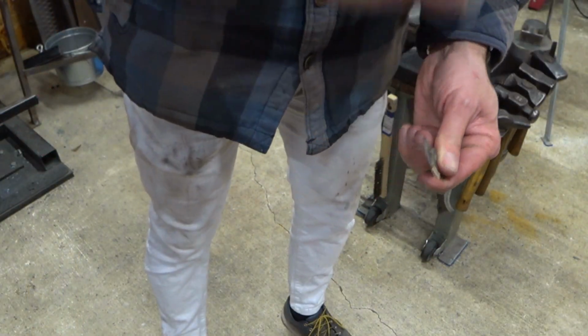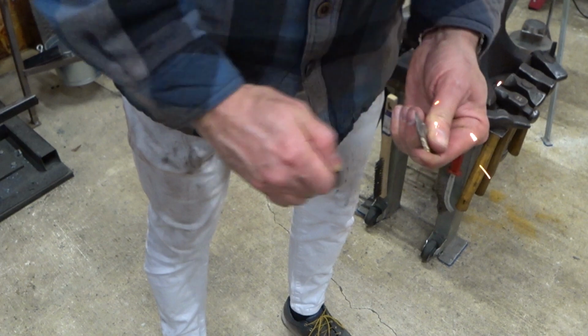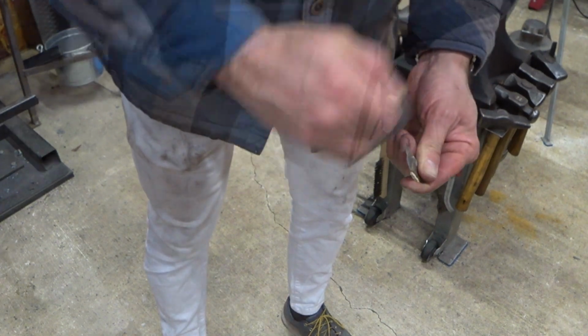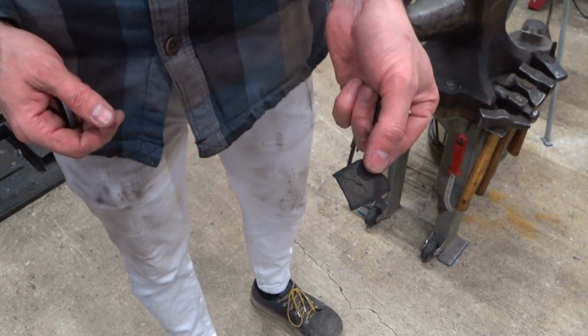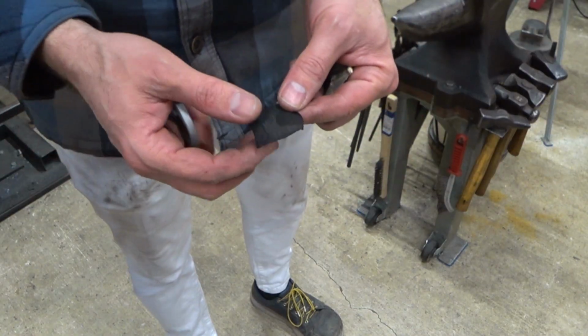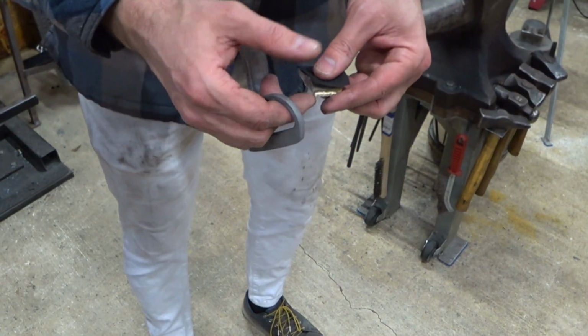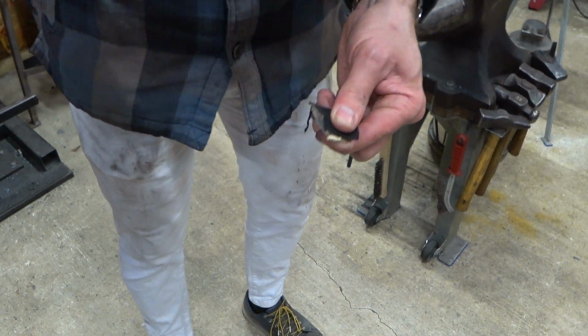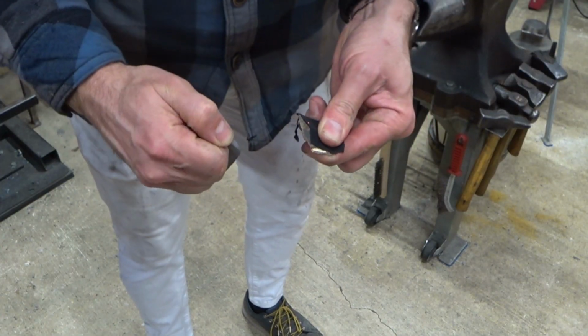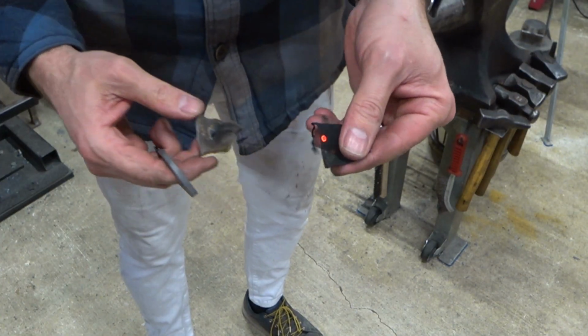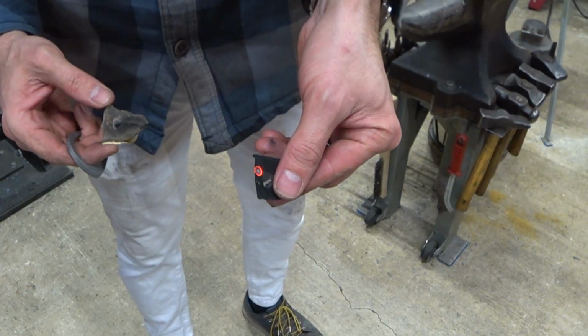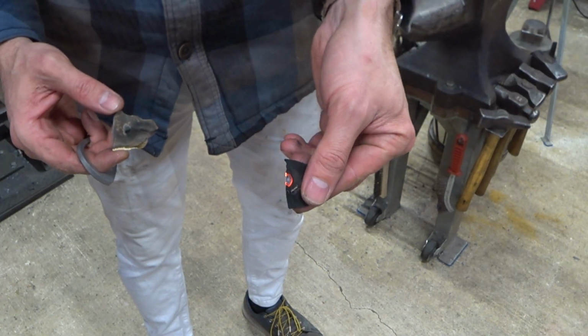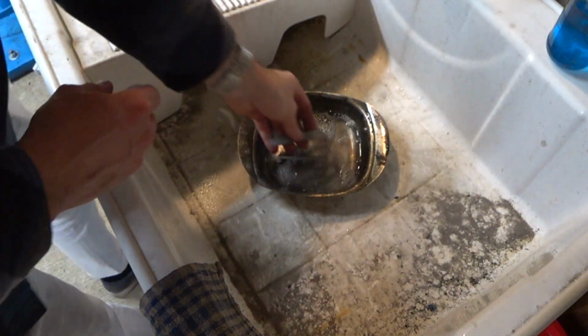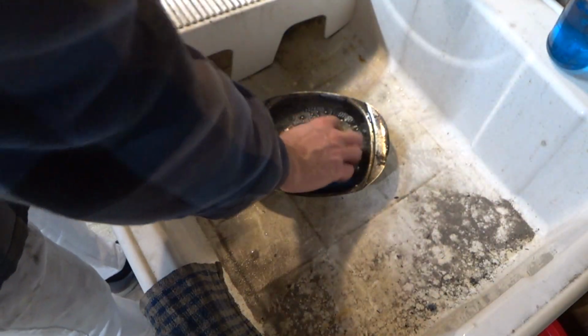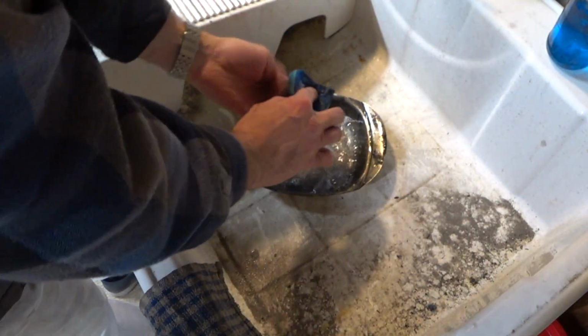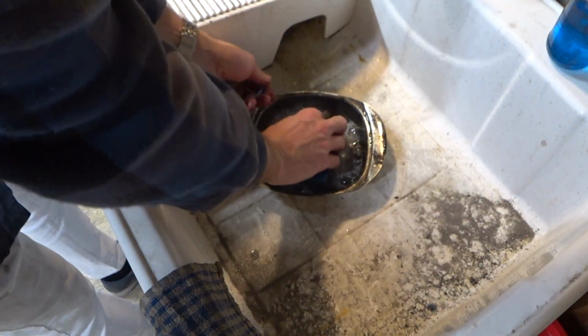Okay, let's test it out. You can see here that we're throwing pretty decent sparks. And this is not that sharp of a piece of flint either. So to actually start a fire, you would use a little piece of char cloth like this little square here, and then hold it up against the flint. And that way when you strike it, the sparks will shower down onto it and give you something to light your fire from.